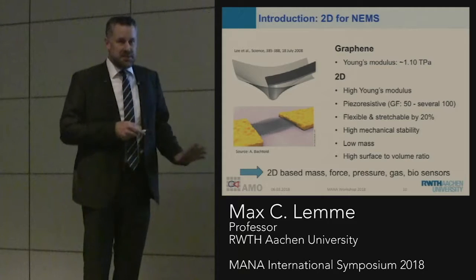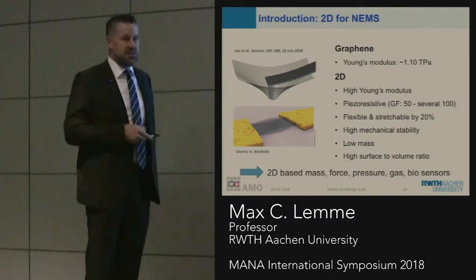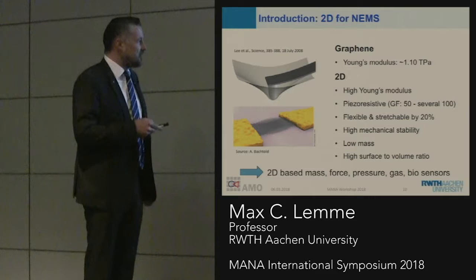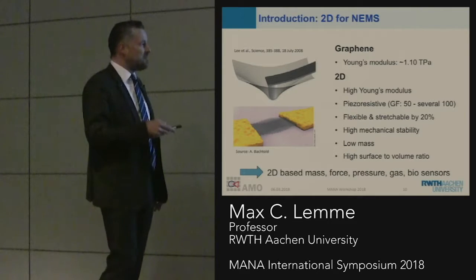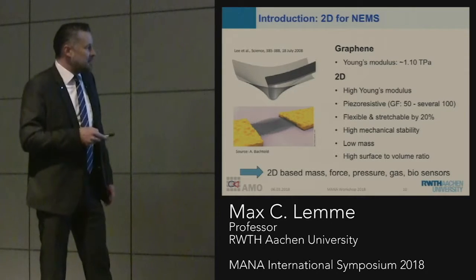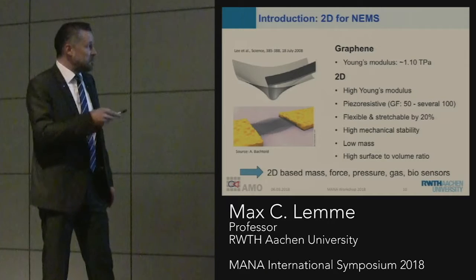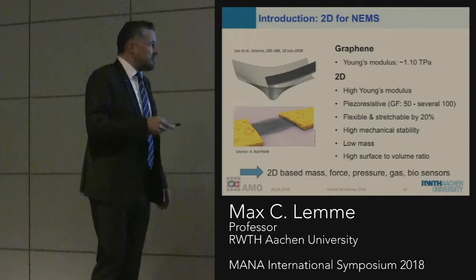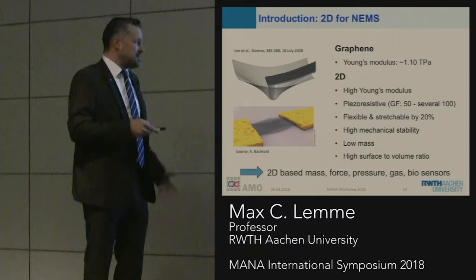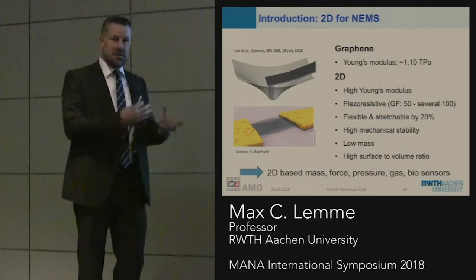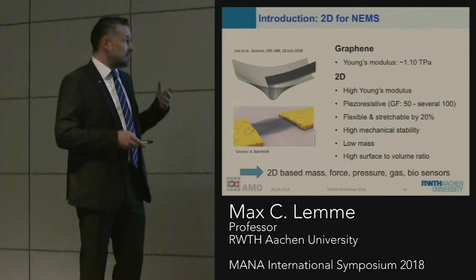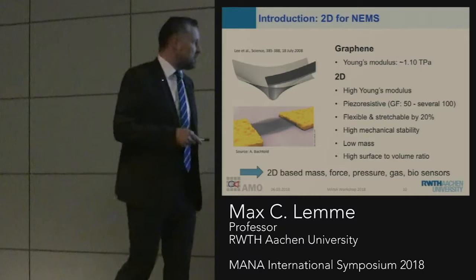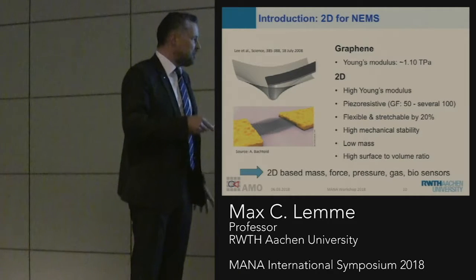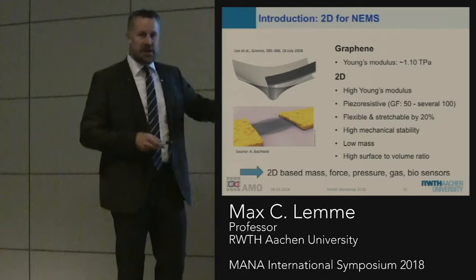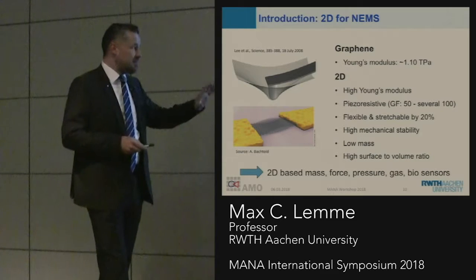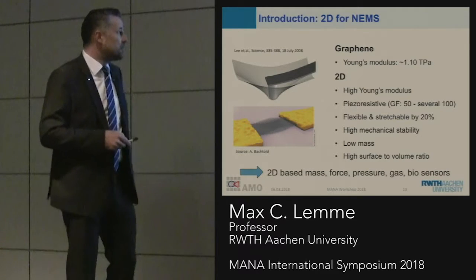These materials are piezo-resistive, so we can use them as transducer materials. The gauge factor of the 2D materials can be between 50 and 100 or even more. They're flexible and stretchable by up to 20% in the case of graphene, mechanically stable, low mass, and have a high surface to volume ratio. All these properties indicate that the materials should be good for 2D based mass, force, pressure, gas, or biosensors, so all kinds of sensors should be highly sensitive when using these materials.